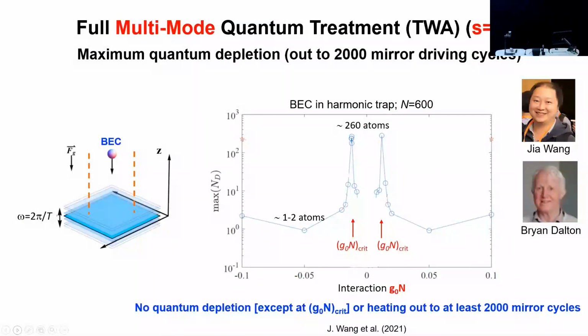Okay, so Bryan and Jia did the big complete calculation using a multi-mode quantum treatment for the case S equals 2. And this calculation is for the maximum quantum depletion, studying the quantum depletion as a function of interaction strength. And you find that there's no loss of atoms except at the critical point. So there's no quantum depletion essentially, except at this critical point, or any heating out to at least 2000 cycles, which is much larger than you could do in an experiment.